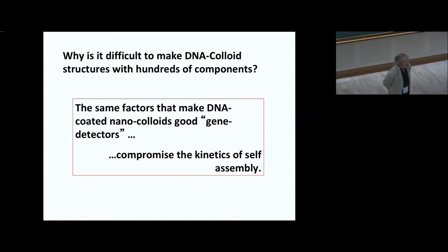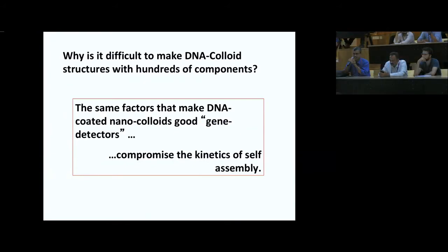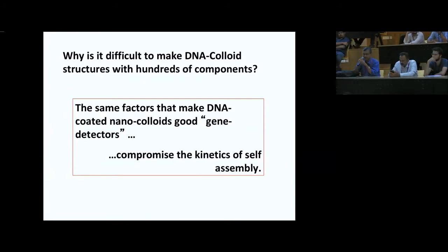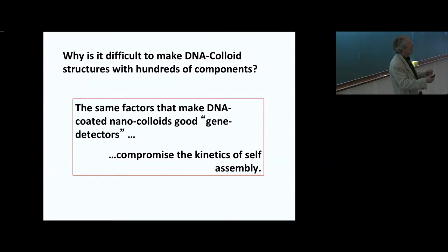DNA contour length fluctuation is rather large. Like if I have two colloids connected by a DNA length of 65 or 100 base pairs, the fluctuation of the length of the distance between them, that's quite significant. It depends a bit on how you do it. But I mean, some people have used flexible spacers and then a sticky end. And there's others that have used rigid things. On the whole, for the flexible ones, yes, you have fluctuations, but basically you can approximate this as Gaussian, and it doesn't create any special complication.